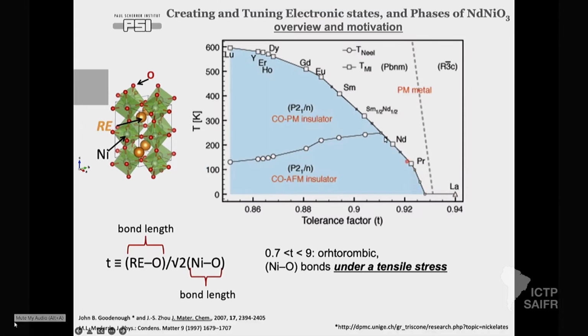So if the tolerance factor goes lower, you are then changing the metal insulator transition very much up. So for something like samarium nickelate, or a compound which contains 50-50 of samarium and neodymium, you go above room temperature. However, the system which is mostly studied is neodymium nickelate, because it turned out that this system is more stable in powder crystal form. Nickelates are very difficult to synthesize and to keep stable at air conditions. However, what is important here is that for all of these systems, the nickel-oxygen bond is under tensile strain. So you have a system which intrinsically has the strain there. There are also some good papers which go from the beginning of this topic, which you can refer to here.